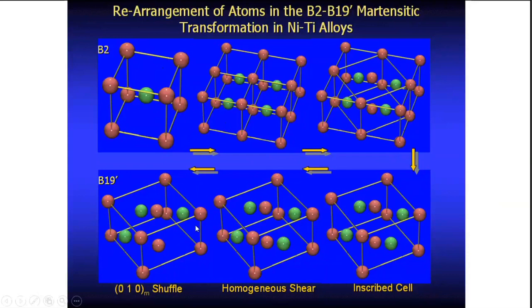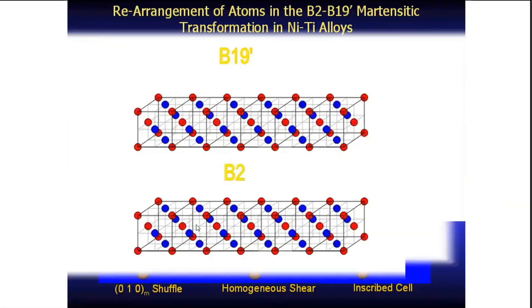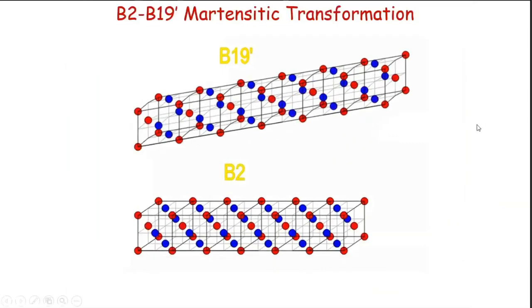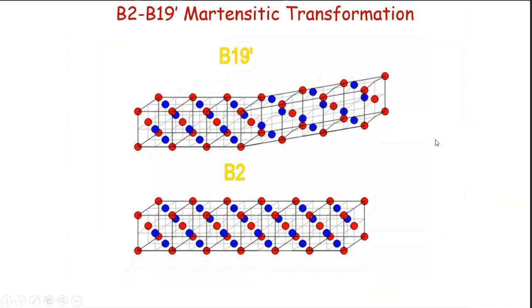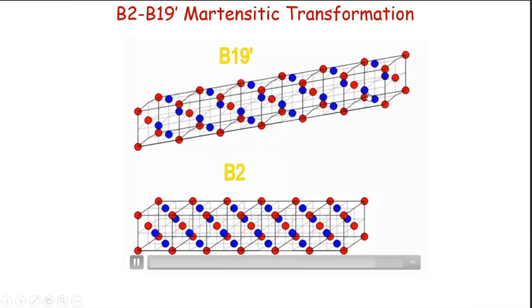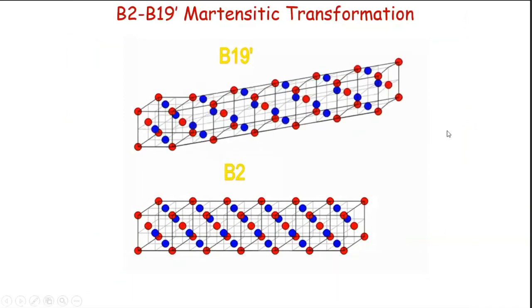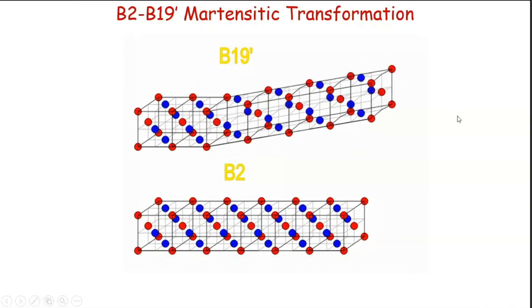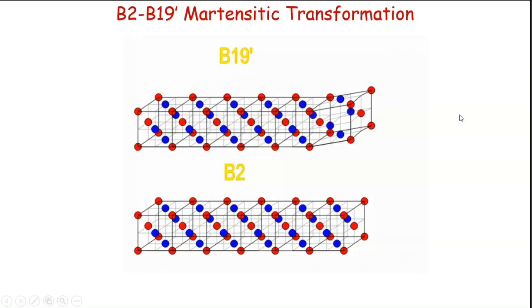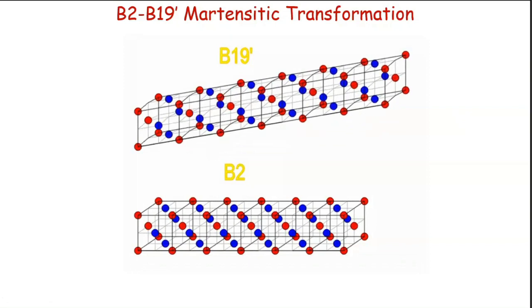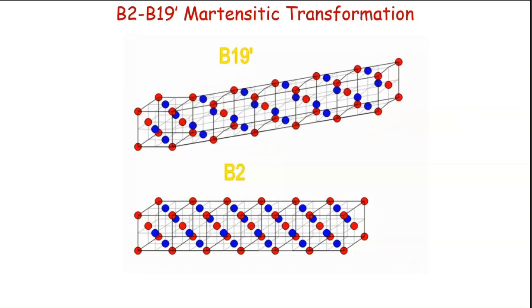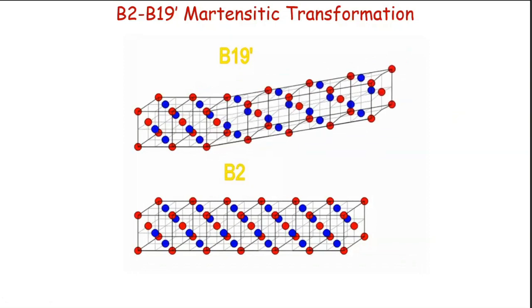So to get out of this very deep explanation and to look at it in a very simple way, this animation helps us there. And you can see you start with the cubic, and this is the delineated cell which has been stacked up. You can see it's quite faithful. If you look at this kind of animation, you can see that there is a shuffle happening. But the picture that you should take away from this is that you're having a shear and there's a change of shape. Now, it is a change of shape that we are looking for. Any shear gives rise to a change of shape. Plastic deformation is also a shear, and that also is required by a change of shape. So here I can deliver a change of shape with this shear. Okay, I move on to the next slide.